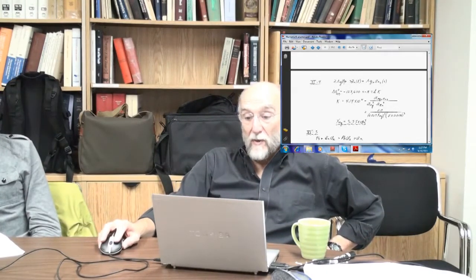Okay, so your activity of the complex is 1 because it's pure. The activity of silver is the activity coefficient times the mole fraction. The activity of zinc is the activity coefficient times the mole fraction, which was a given in the problem, and so you reduce the silver to 10 to the minus 4. And then you end up with this much zinc contamination.